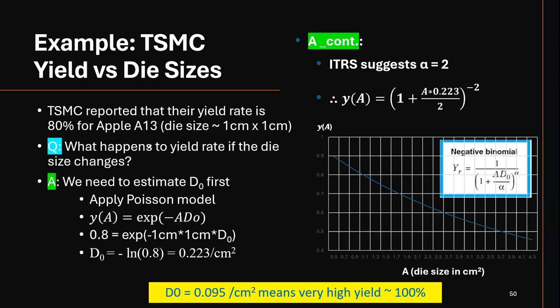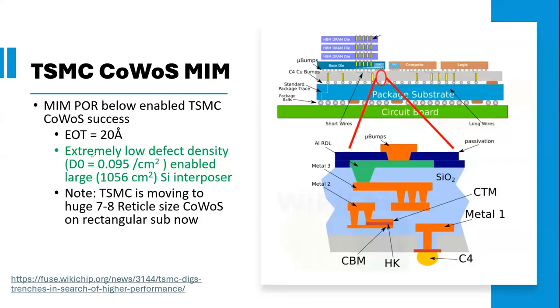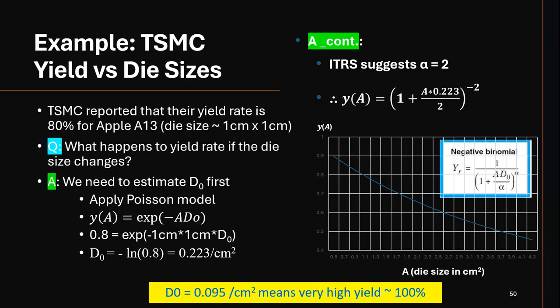And from this calculation, I would like to share with you that the D-naught I calculated for 80% yield with this die size is 0.2. And if you look, they reported D-naught is 0.09, meaning much smaller. That means the yield rate is much larger, right? You look at this Poisson model, exponential, the smaller this number, the closer this one is to 1. So this is what I meant. D-naught is very small. That's the beauty of it.